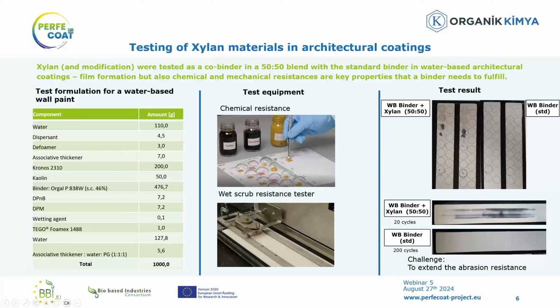For the chemical resistance, basically we make a drawdown and we place different products, so coffee, wine, mustard, as you can see on the picture, for a certain time, exposed directly to the coating, and then we clean it up and we look at the coloration in time. Also you can do the test with some pens, depending on the standards you are following. So you can see that the standard binder doesn't show any, or not too much discoloration, while with the use of the xylan and modification together with the binder, we start to see some discoloration.